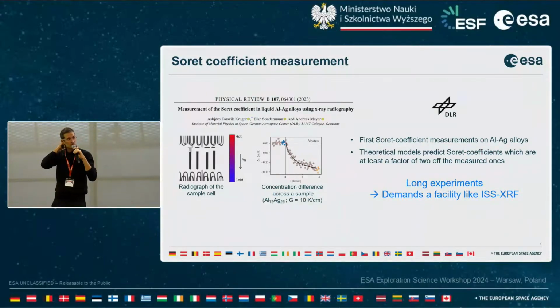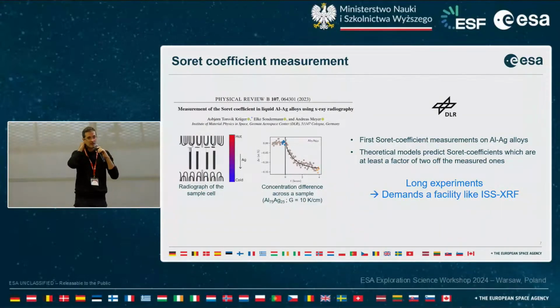There are many works on transparent alloys and fluids, but it is much less common to study that on metallic alloys, especially in situ, as can be done with X-ray imaging. And this was done by our colleagues at DLR, who carried out the first Soret coefficient measurements on aluminum alloy, aluminum silver, where you can see here the radiographs of the capillary samples. And again, by applying a temperature gradient to the liquid alloy, you have a concentration gradient that occurs, which allows the measurement of this coefficient.